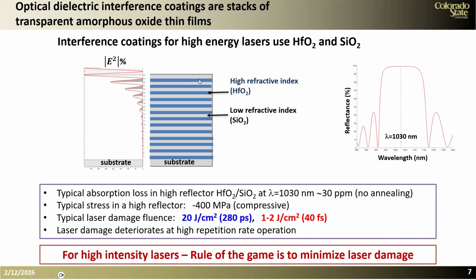Now, depending on the layer thickness and the refractive index, I can use programs to design the optical response. And so, for example, I show here how in this particular case, if we use quarter wave optical thickness, then I will design a mirror in which the reflectance looks like this. This one was designed for a center wavelength of 1030 nanometers. So we can now typically grow hafnia silica coatings at 1030 nanometers with, for example, 30 parts per million absorption loss without annealing. The challenge is that when we grow these coatings, they will have high stress, which is 400 megapascals. And their laser damage fluence is of the order of 20 joules per square centimeter at 280 picoseconds.